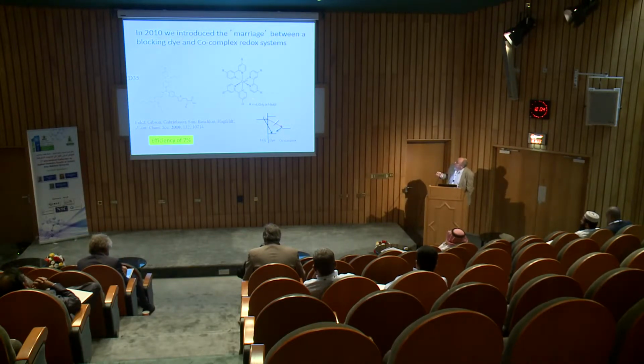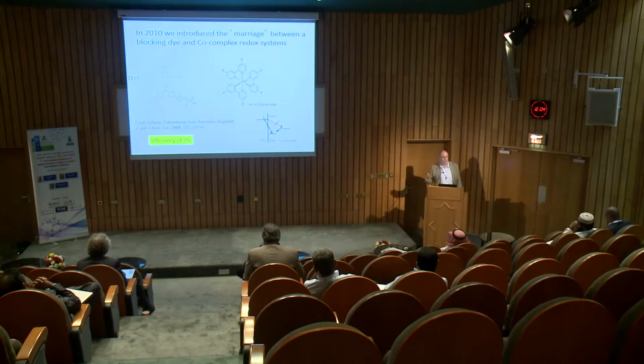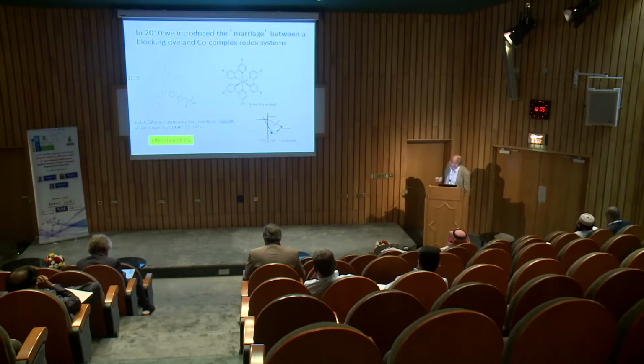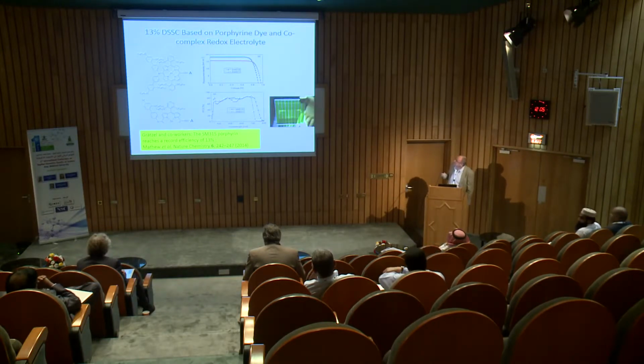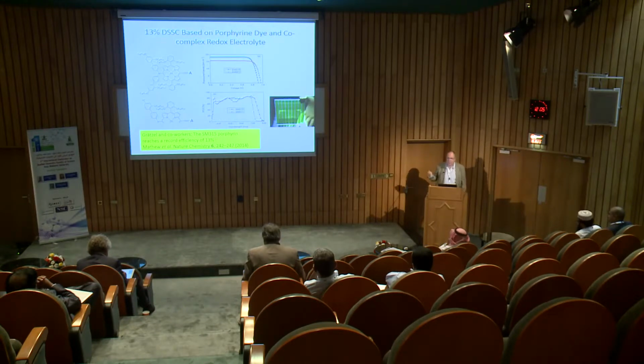And then our first choice to try something else than iodide was to use this cobalt 2+/3+ complex. It's a bipyridinium complex, and very early on we got nice efficiency with this one, and we had presented 2010 about 7% efficiency with this system, which was the highest at the time for something else than the iodide triiodide electrolyte. Then this created a lot of interest, and EPFL and Professor Michael Gretzel, I remember, called me once and he said, well, you are right with the cobalt, now we have 9% efficiency, and it also increased,